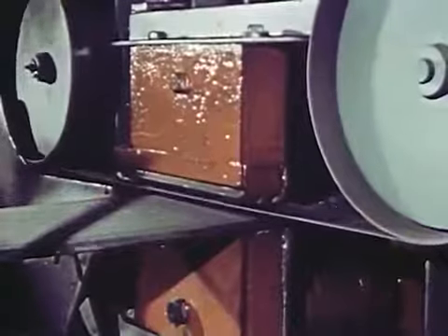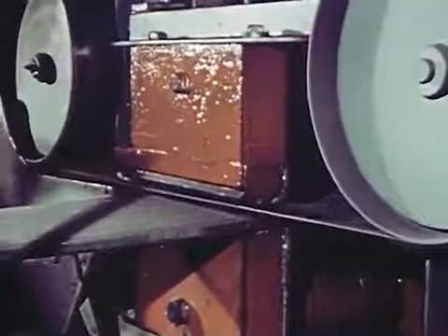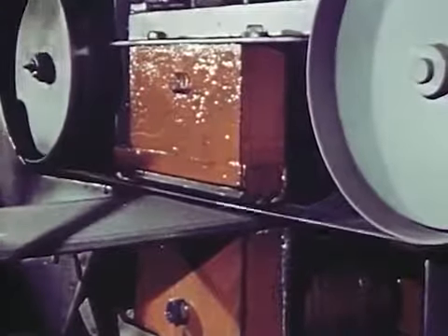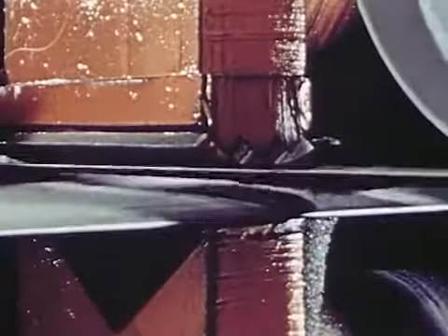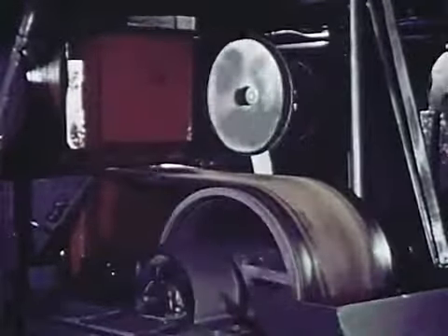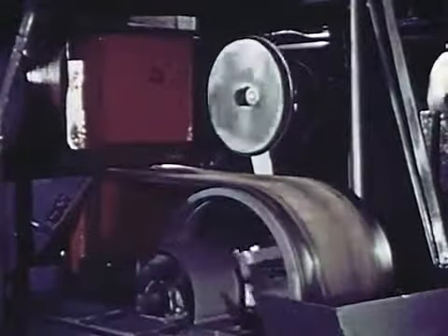First, to be sure the ilmenite is shipped as the purest practical concentrate, it is passed through a low-intensity magnetic separator to remove any remaining magnetite. The small belt passes under the electromagnet and at right angles to the broader feed belt, from which it picks up the magnetite. The feed then passes under a high-intensity magnet that separates the ilmenite from traces of waste materials.